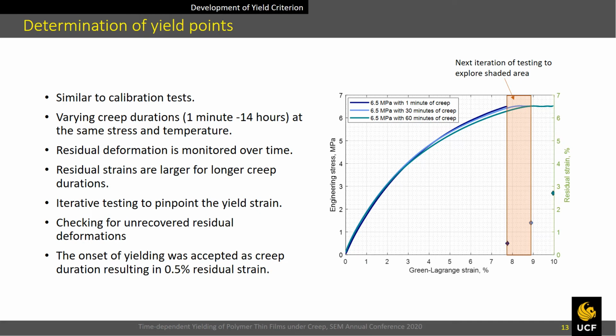We are interested in the creep duration that results in minimum non-zero residual strain. The onset of yielding was accepted as the creep duration resulting in 0.5% residual strain after 24 hours of free recovery at room temperature.